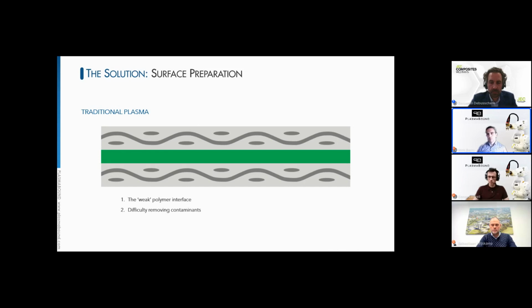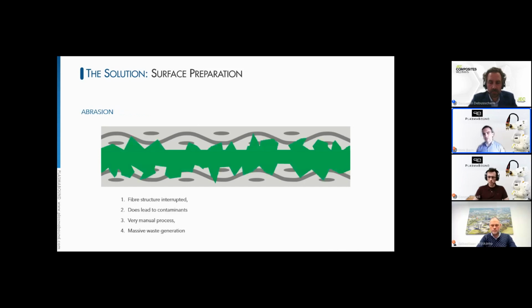When we look at abrasion, which everybody probably here is aware of, we again see an increase of the surface free energy requirements, and plenty of adhesives are designed to match it. In fact, almost all adhesives are designed to have an increased dispersive component. However, fiber structures near the surface are interrupted, leading to residual stresses within the interface, and does lead to contamination within the surface, requiring further cleaning more often than not. And it is a very manual process. It's not suitable for high volume continuous manufacturing, and there is massive waste generation and disposal of grit and cleaning effluent, which doesn't really match up with the future focus that we have within Europe and within the world really at the moment.